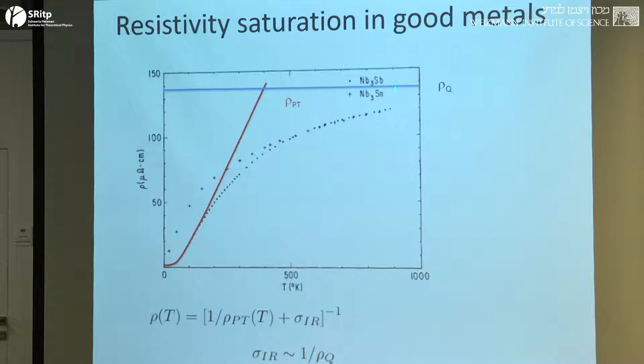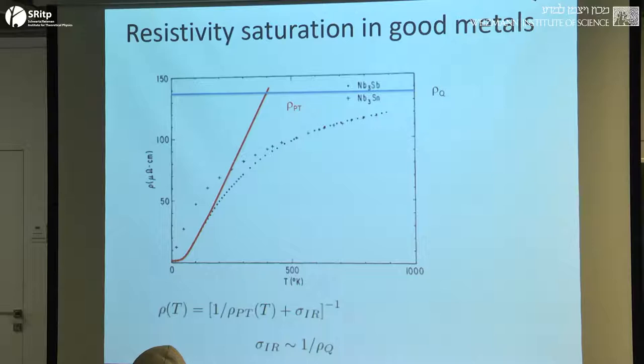And the A15s, I mean, I think there's still interesting physics to go back to about the A15s, but to zeroth order, I think the understanding was and still is that the reason the A15s were particularly good superconductors was that they were metals with particularly big electron-phonon couplings. And that both allowed them to become superconducting at a high temperature, but it also meant that when you do the usual Boltzmann transport theory, which works quite nicely at low temperatures, you very rapidly get to values of the resistance that are approaching this quantum of resistance. And at that point, the quasiparticle picture breaks down.